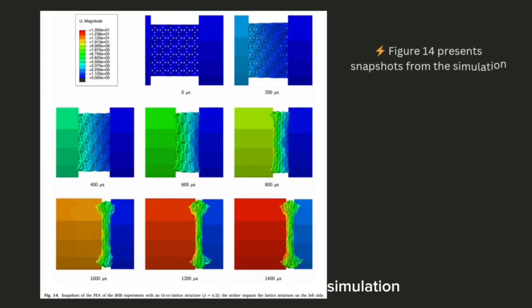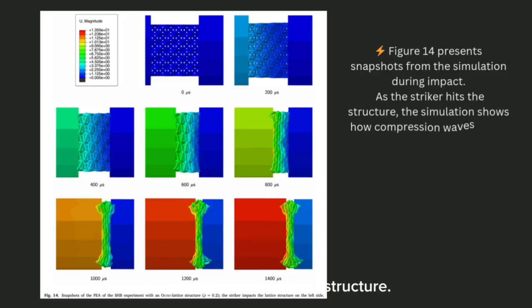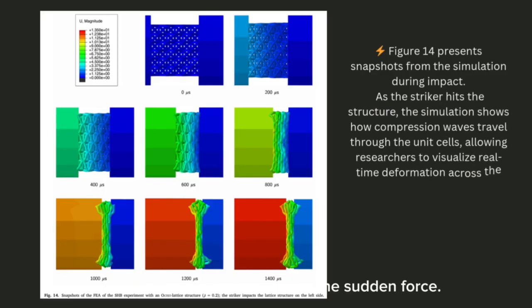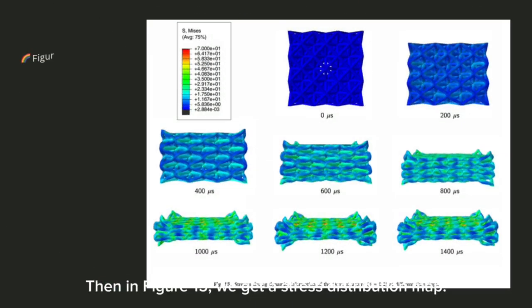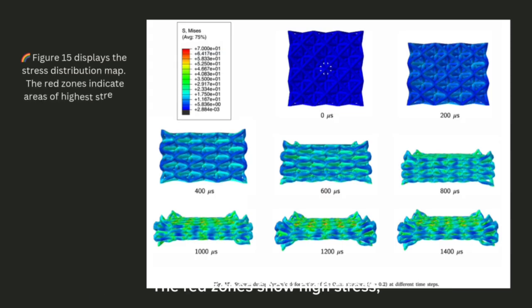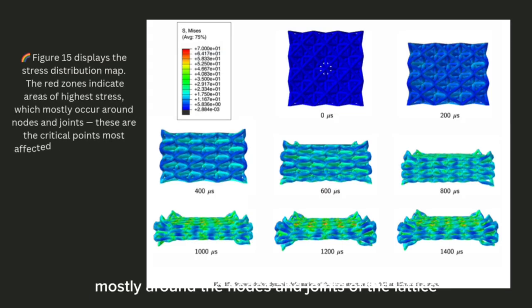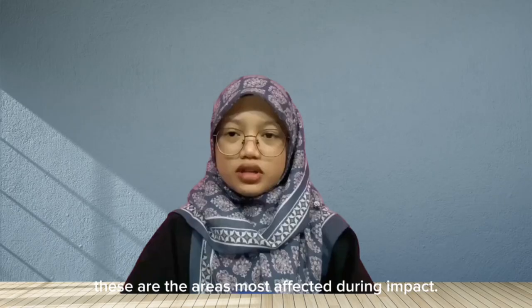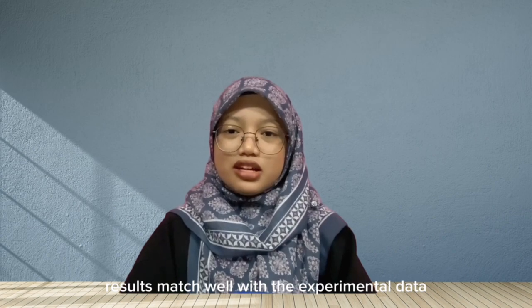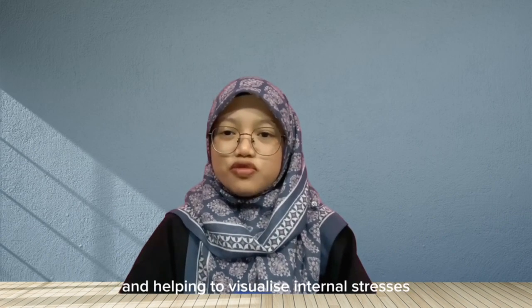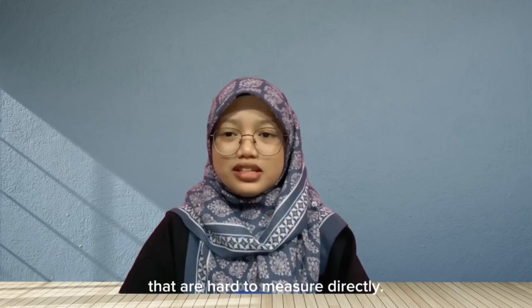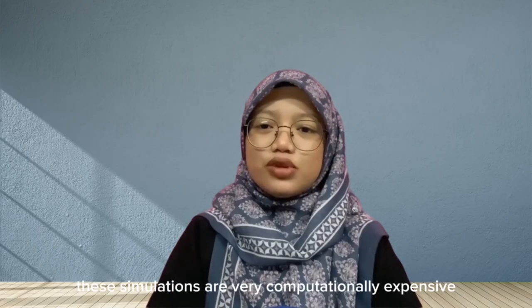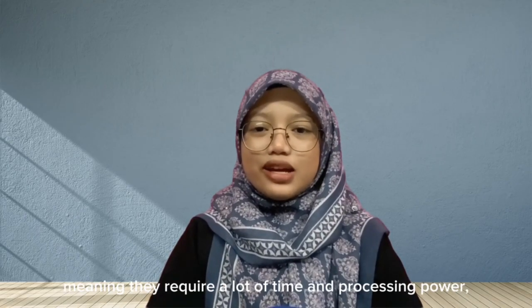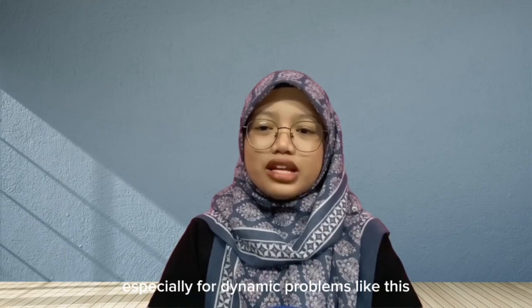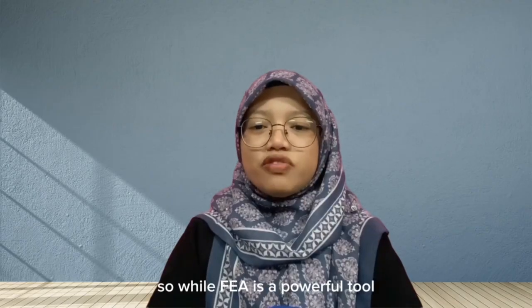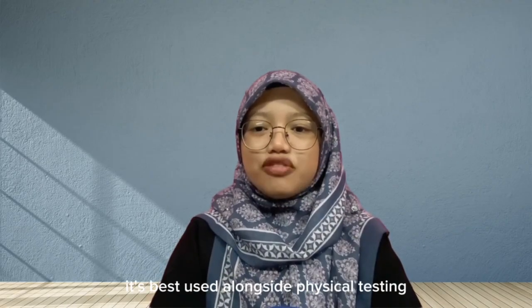In figure 14, we see snapshots from the simulation as the striker impacts the structure. It shows how the compression spreads through the unit cells and how the structure reacts to the sudden force. Then, in figure 15, we get a stress distribution map. The red zones show high stress, mostly around the nodes and joints of the lattice. These are the areas most affected during impact. The simulation results match well with the experimental data, confirming the accuracy of the physical test and helping to visualize internal stresses that are hard to measure directly. However, the authors mentioned that these simulations are very computationally expensive, meaning they require a lot of time and processing power, especially for dynamic problems like this. So, while FEA is a powerful tool, it's best used alongside physical testing for full understanding.